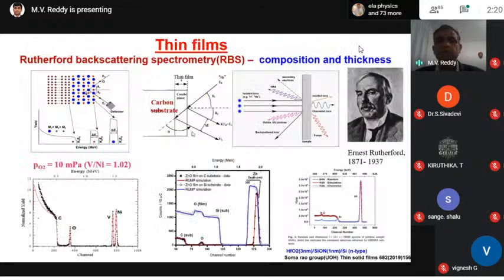So these are typical RBS, Rutherford backscattering spectra of thin films. When the helium beam hits the particular thin film, we measure the backscattered energy. The usual practice is that higher atomic number will have higher channel number. Based on the RUMP program, we know the composition and especially the thin film thickness. So we can calculate the composite thickness of the thin films. This is one of the best.